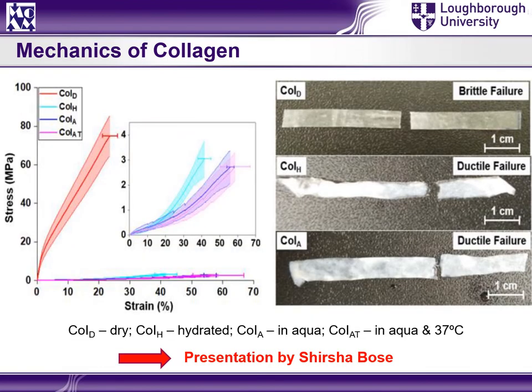And here is a very important point about the effect of the environment. Dry materials are significantly stiffer, by orders of magnitude, compared to wet ones. The inset here shows the level of the strength. Importantly, the ductility is changing dramatically as well. Dry materials perform nearly brittle, while the materials exposed to the fluid demonstrate a much softer behavior, but with strains at failure which significantly exceed those of the dry specimens. As a result, we see that these materials demonstrate a ductile failure.